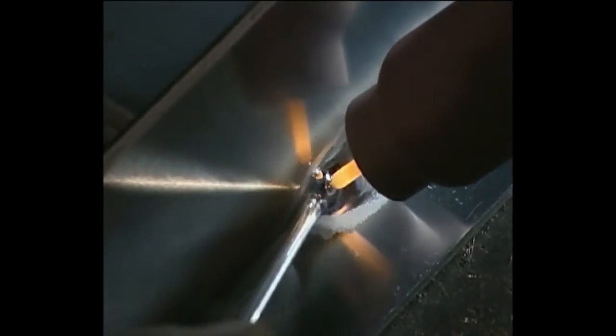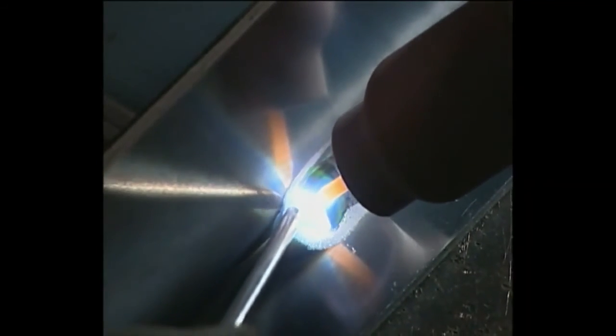With horizontal fillet welding, heat will concentrate on the vertical plate side, which tends to melt first. To accommodate this characteristic, slightly shift the aim of the arc to this side of the horizontal plate rather than focusing it on the corner. Try to heat the horizontal and vertical plates at a ratio of 6:4 so that a pool forms on both plates simultaneously.